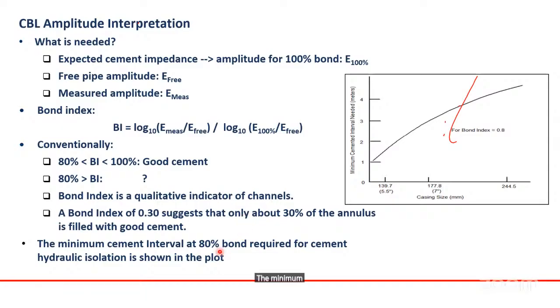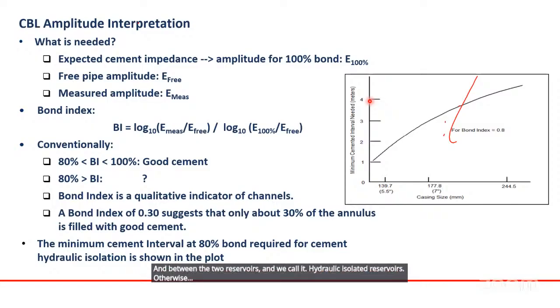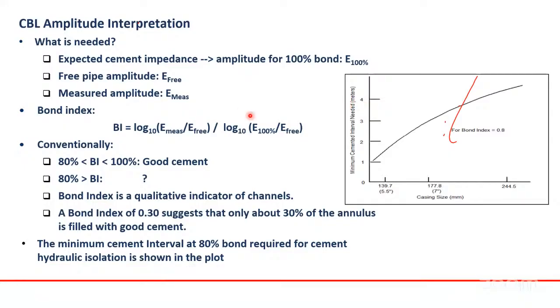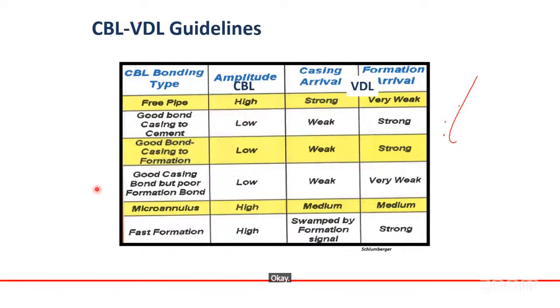The minimum cement interval at 80% required for cement hydraulic isolation is shown in the plot. If we have, say, a 9 5/8 inch casing, we need at least 4 meters, about 12 feet of good cement between the two reservoirs, and we call them hydraulically isolated reservoirs. Otherwise, they have to do a remedial action. This is just a guideline for the interpretation of the CBL bond, CBL and the VDL.